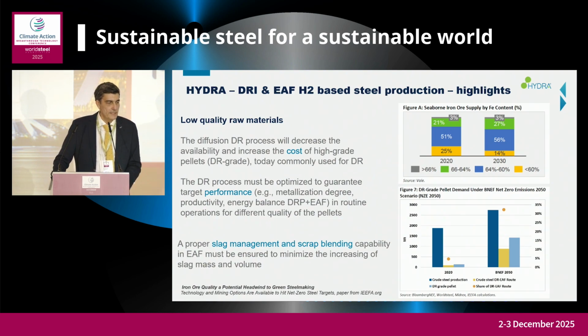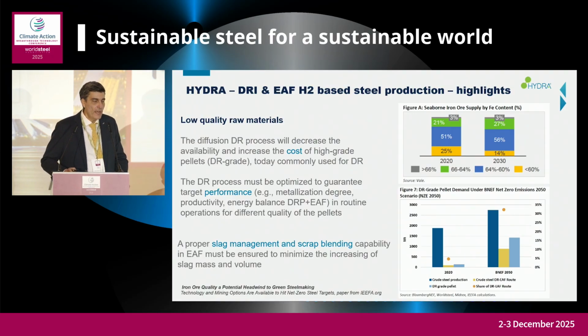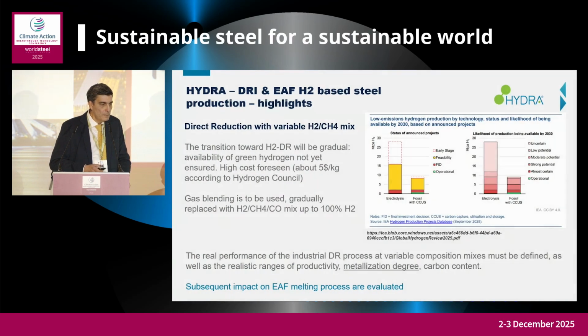When I say working on the melting step, I mean proper slag management. For us, slag composition, but also refractory composition, is not a religious dogma. So we are working at this moment with the support of calculation codes, but once the facility is ready, we are going to test with our experimental facility how we can better manage, if possible, the process according to the amount of gangue that is present in the DRI. Another aspect is the blending with scrap. That is the other aspect which we can modify in order to accept also low-grade materials. And another aspect is the hydrogen availability.